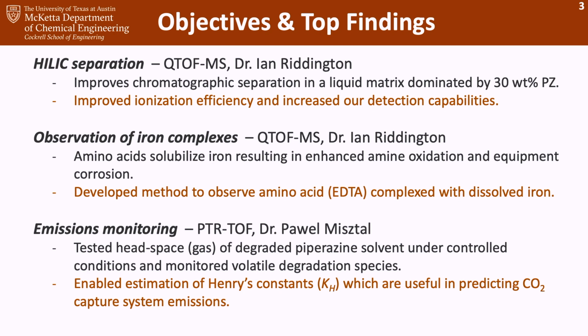Finally, with the help of Dr. Pawel Misztal, we're able to use his Vocus PTR-TOF to monitor emissions. By doing this, we're able to test headspace gas of degraded piperazine solvent under controlled conditions, and this allowed us to monitor volatile degradation species. With this information from both our liquid and gas phase analyses, we're able to estimate Henry's constants, and these will be very useful in predicting CO2 capture system emissions.